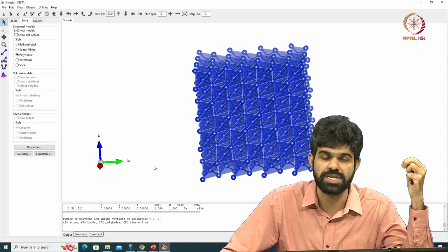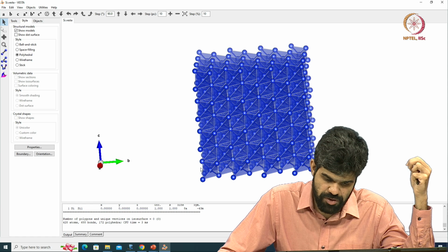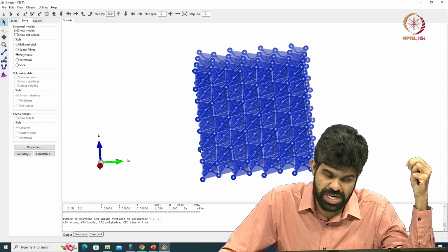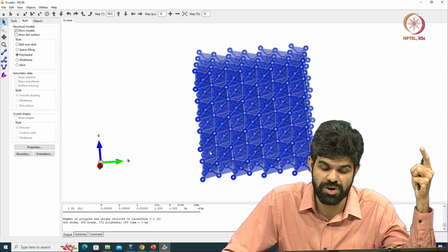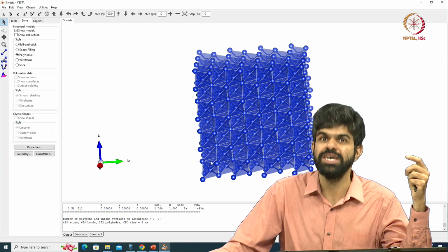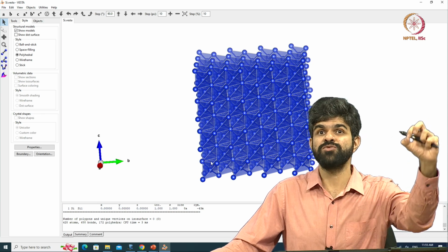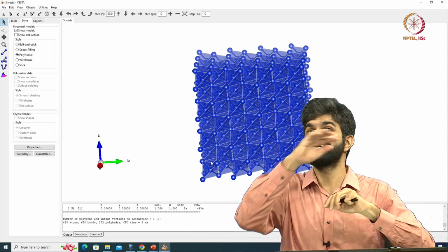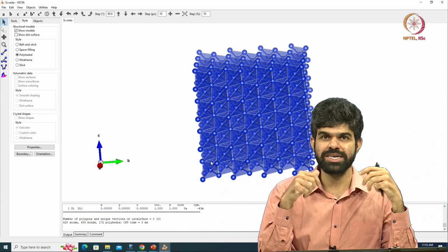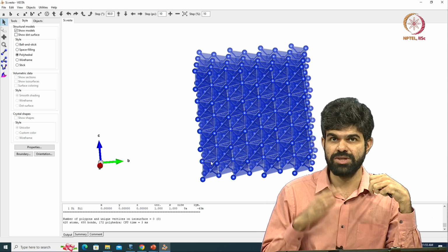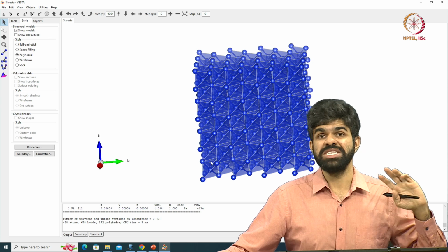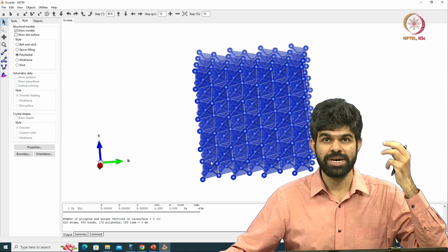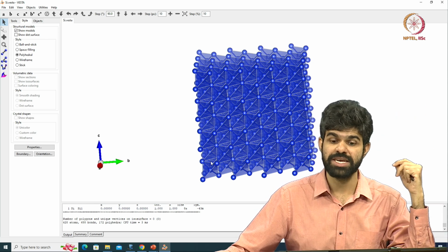I do not know if you can see this. So, it is perpendicular to my four-fold axis. So, this plane is a mirror plane. This silicon should be reproduced here ideally, but since there is a glide, a diamond glide, it will be reproduced at one of these tetrahedral positions, right. So, all the tetrahedral positions, the 1/4, 1/4, 1/4, are created by a diamond glide. That probably you can try to geometrically visualize yourself, right. I am just rushing through here a bit. So, this is equivalent to having a diamond glide. The tetrahedral positions, or everything, is filled by silicon.